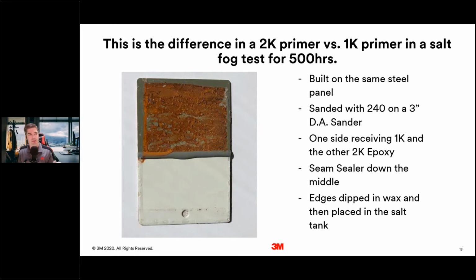And it's important to point out that when we do these coupons, we only put one coat of epoxy on here, not saying we want to skip a step. In fact, we've had several paint companies say, hey, we're concerned when you tell technicians that you're only using one coat of epoxy. We always recommend two, and they have to follow our directions for use. And we say, we know and we understand that, we point that out, but we do it this way because we want to show the strength of a 2K epoxy primer versus 3 or 4 coats of a 1K primer on that bare metal surface.